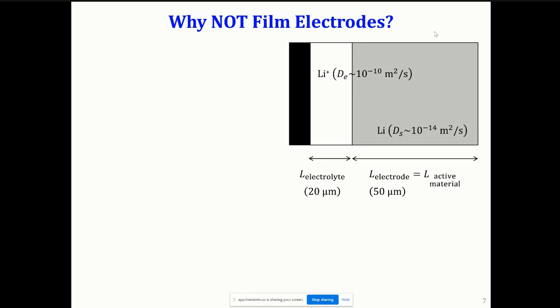Now what one can do after this is define some time constants, which is essentially nothing but the lengths divided by the respective diffusion coefficients. As it turns out, a representative time scale for lithium to diffuse in the active material would be about 70 hours if we start with this configuration. And correspondingly, the time scale for electrolyte diffusion, Li+ diffusion in electrolyte, would come out to be 4 seconds.